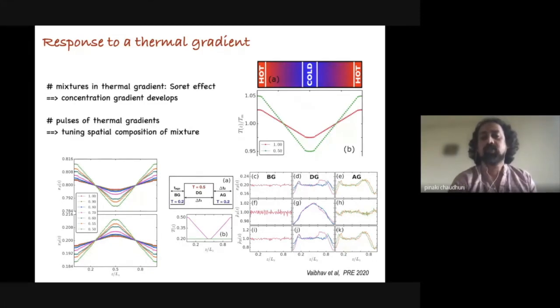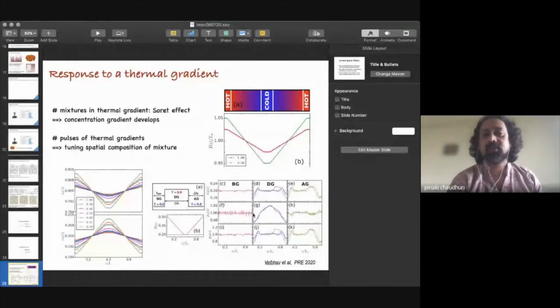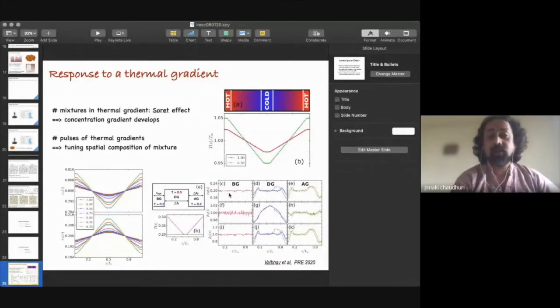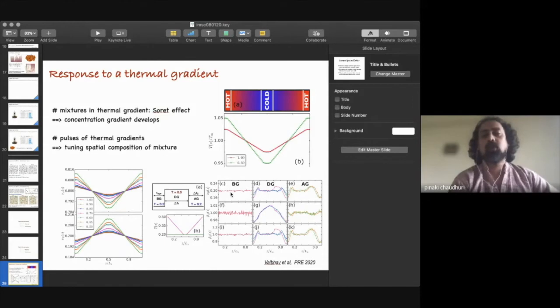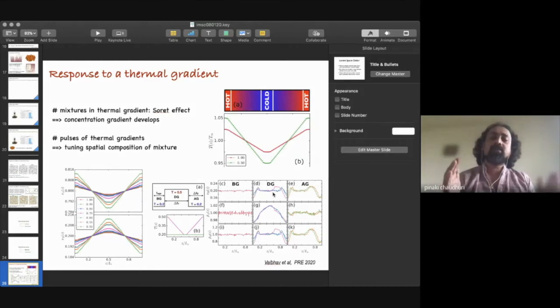plot. So if I just switch to the, because I think without the cursor it's becoming difficult to show. Yeah, sure. So here, the ambient temperature is below the glass transition temperature. So here I have a concentration profile which is flat, and as I switch on the thermal gradient, the concentration profile starts changing because there is a region which is getting melted because of the high temperature, and this melting front starts propagating into the system.